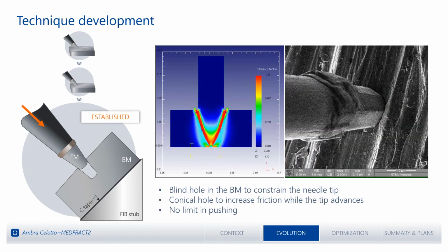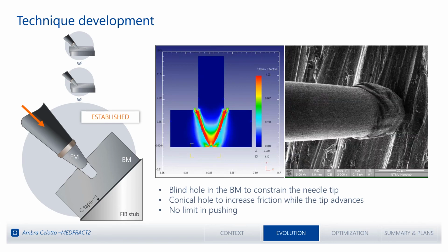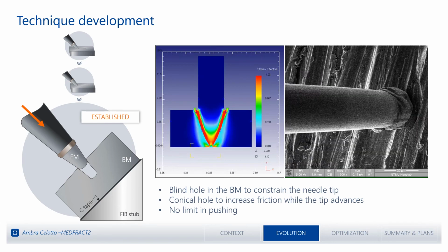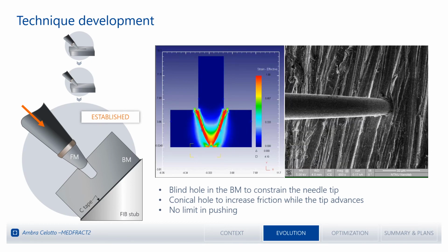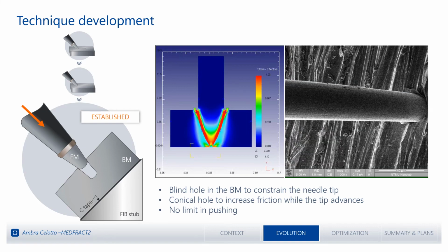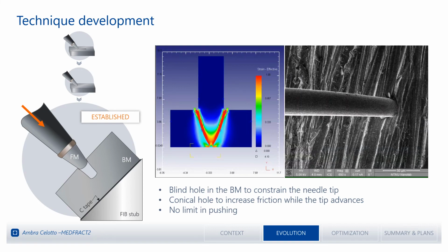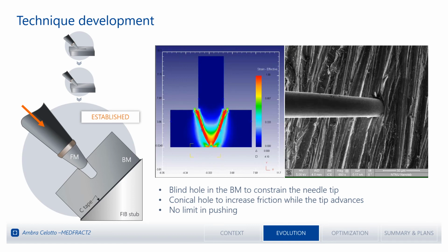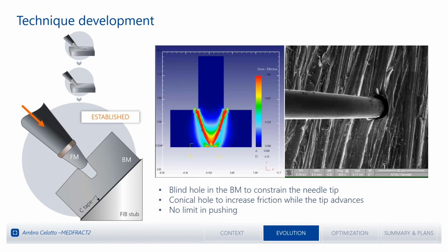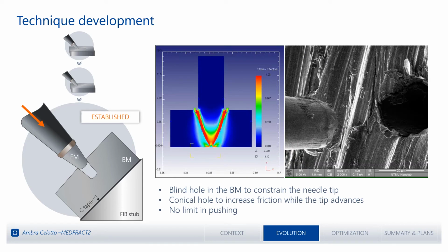So in practice, what happened was something like this. Here the needle is pushed inside the hole. There is a slight misalignment because the base metal is sliding, so this has to be optimized, has to be improved. But one thing, we were actually able to push it with no limits inside the base metal. And then when the needle is retracted, there is no tip sticking on the tungsten needle. And this meant to us that, of course, there was something stronger retaining the filler metal tip inside the hole.